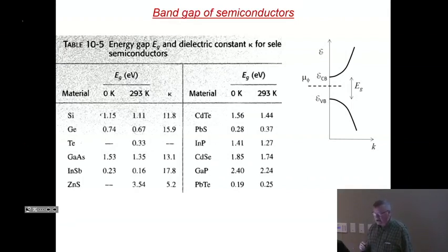In germanium, on the other hand, we have 0.67, so we have a much higher probability to have some thermally excited carriers. If we go to indium antimonide, we have 0.16. In fact, we have a very high probability, e to the power, let's say, 0.025, 0.03, so down to the power -4, so that they get excited, and that's quite a lot. Since on top of that, the electrons in the conduction band of indium antimonide are very, very mobile, the thermally excited electrons will really dominate transport much more than the localized heavy holes.